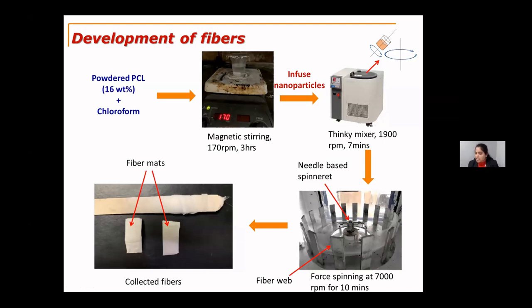And I use a 24 gauge needle here because we are using nanoparticles. If I use smaller gauge needles, these nanoparticles block the needle and the fibers are not generated. So I chose a 24 gauge needle. And then I spun these fibers at 7000 RPM for 10 minutes.